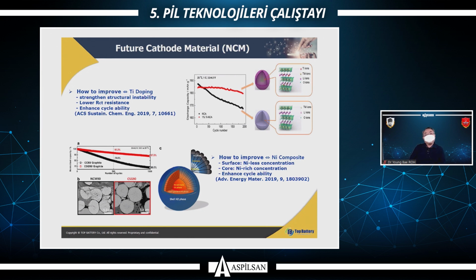Second, the partial crystalline structure turns out to be good for the cyclability. Partial structure means the surface has nickel-less concentration. The core has nickel-rich concentration. One material supplier in Korea is now producing this kind of material in mass production.